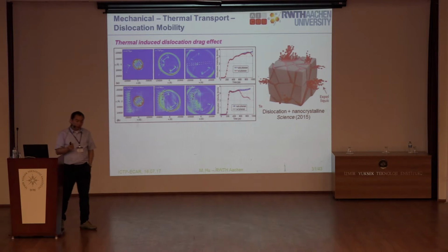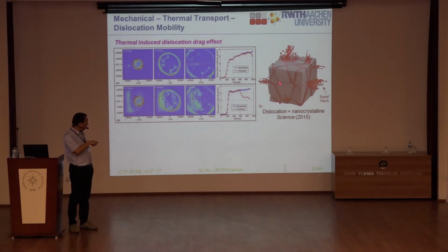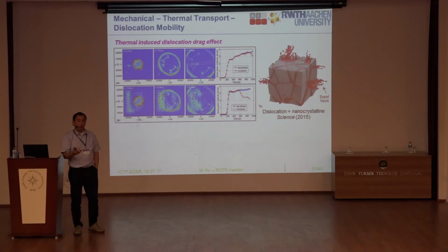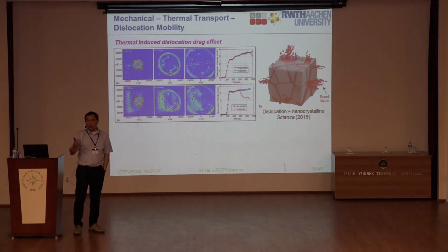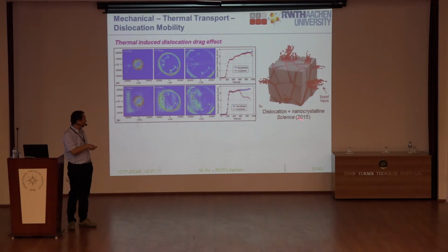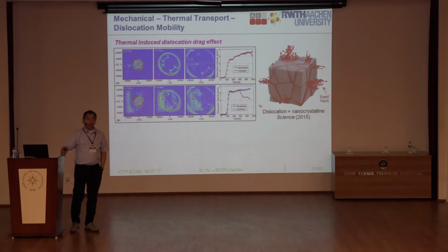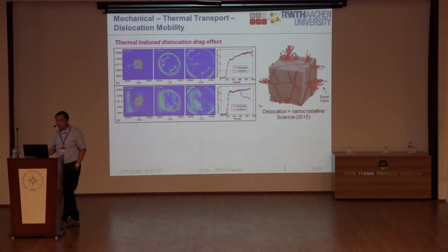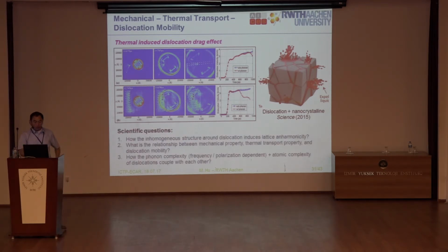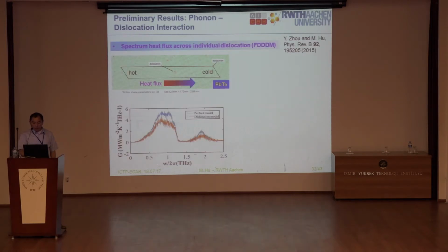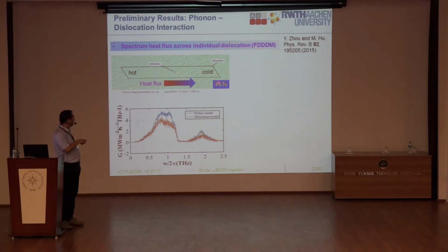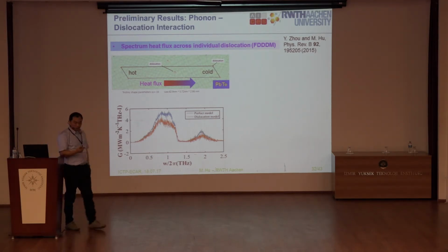So you can introduce the dislocation, concentrated on the boundaries of these grains, and then the dislocation can further decrease the thermal conductivity, right? And this is without significantly decreasing the electronic transport. So this Science paper is also about thermoelectrics. So you can use this idea to enhance the Seebeck coefficient. Of course, there are some scientific questions, and I don't need to repeat. So our model is very simple. It's just the PbTe. Lead telluride is a very good thermoelectric material.